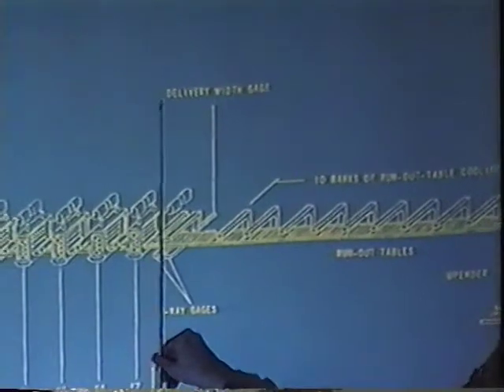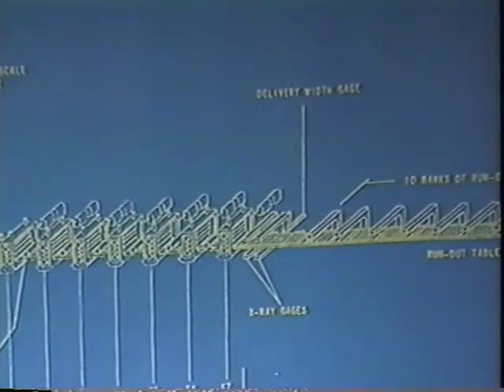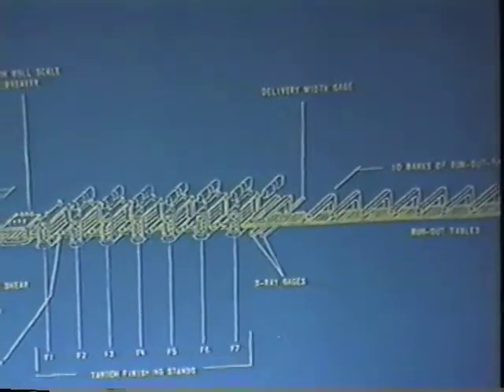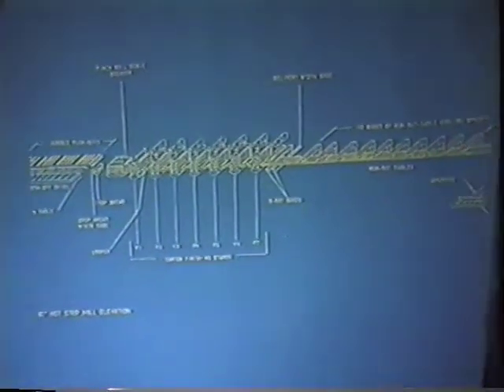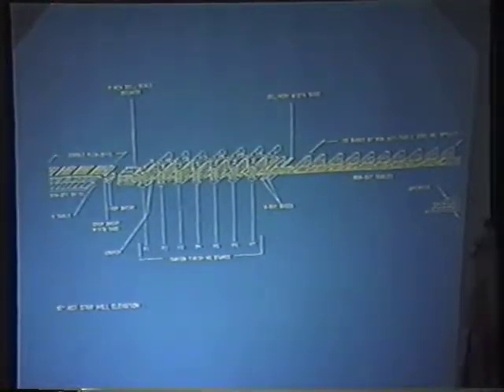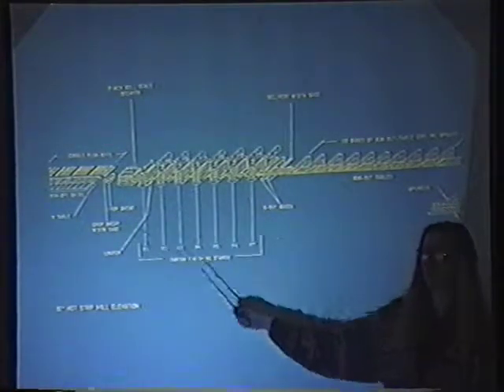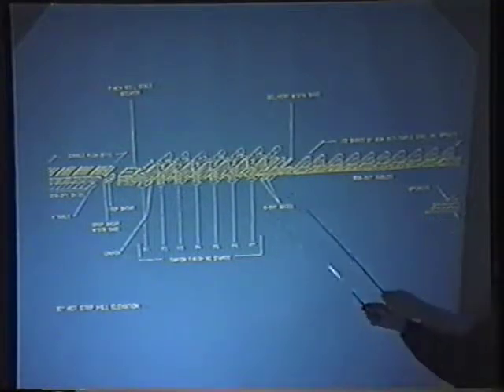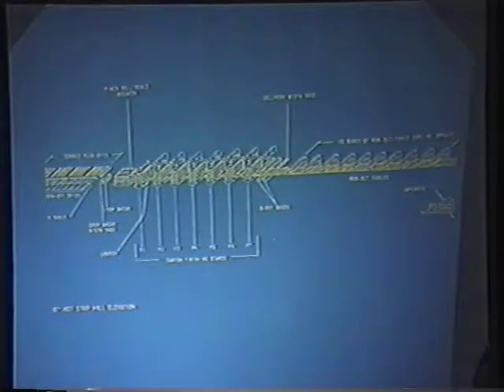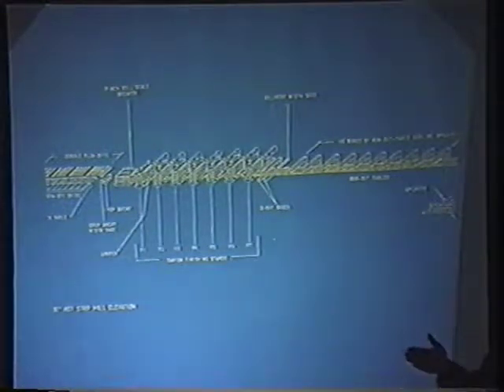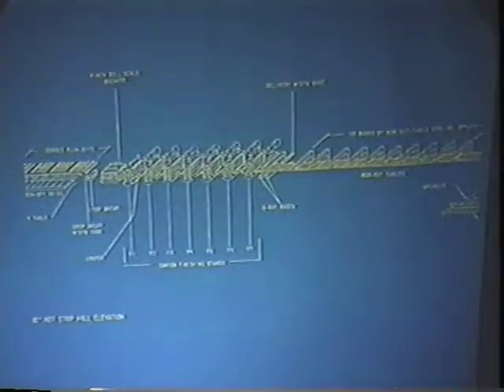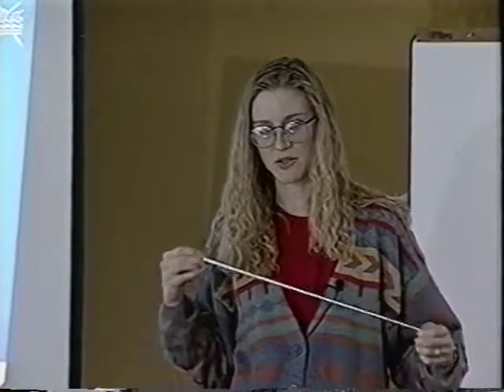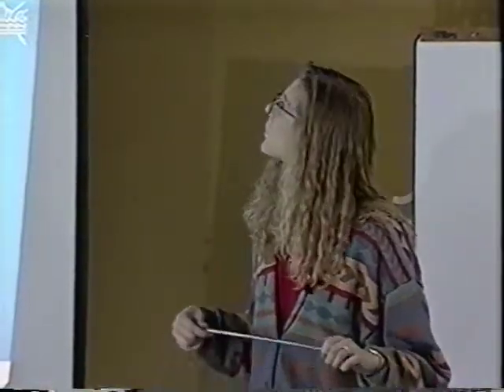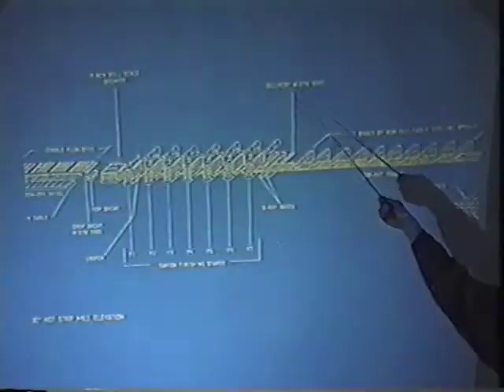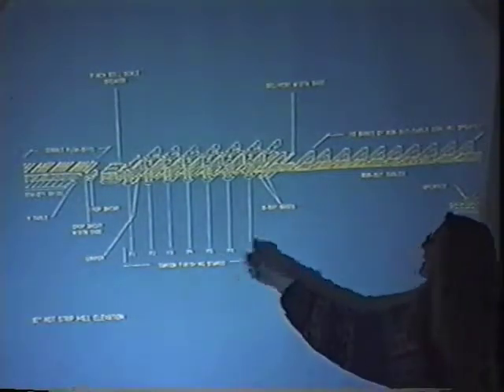By the time it gets to here, it is still above the steel's transformation temperature, which is based on chemistry for the most part. The Met department that I'm in, we set those temperatures, which on average is 1600 degrees. So even with all this water and work being done here, you only lose about 300 degrees. Next we have some x-ray gauges. We have a stationary centerline x-ray gauge, and a traveling x-ray gauge that moves across the strip to give us a profile. We can guarantee profile out to within 2 inches of the strip. With our new equipment, we'd like to move that out to 1 inch or even further. We'll try. And we also have another width gauge on the outside. We have one here and here.